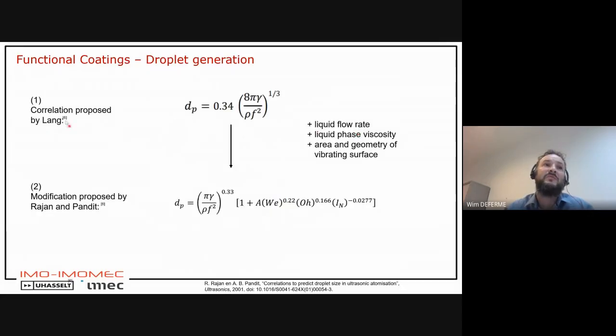And the first one was proposed by Lang, where you see here the correlation between the droplet size and the applied frequency, the surface tension of your liquid, the density of your liquid. So this is a material-based relationship. But of course, it was modified a bit by Rajan and Pandit some years later, where they show that it depends on your material properties, but it also depends, like you see here, on the Weber number, on the area that you apply. So it also depends on your jetting properties. So this is very important, that you have a combination of material-based properties and jetting properties to define the droplet size of your droplets that you generate. So you have relationships between them.